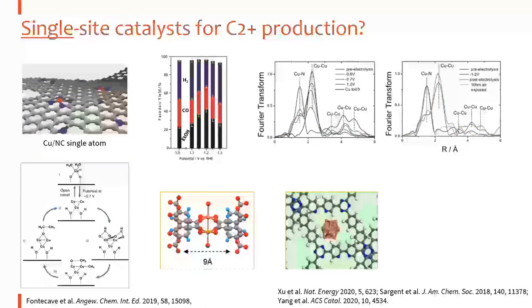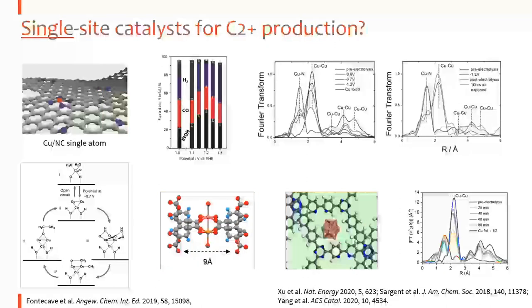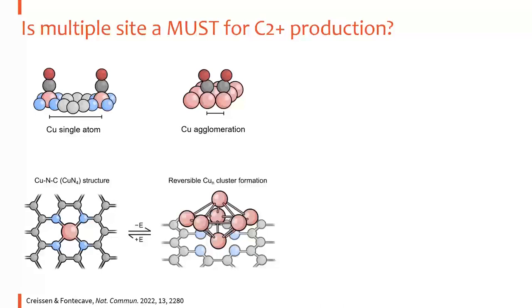Actually, several more examples have appeared after this work, using different materials like oxygen-coordinated copper, MOF, and COF, and they found similar things. That is, even if it's a single atom catalyst in your precursor or prior-to-electrolysis material, under operating conditions they become copper nanoclusters instead of single atoms, so that the copper nanoparticle is actually the real catalyst during the reaction. This is not so difficult to understand, because for the single atom, the copper-copper distance is quite far away. It's very difficult for two CO to couple together to form the OCCO intermediate for the C2 product. But once the copper cluster forms from the single atom copper, the copper-copper distance is quite close.